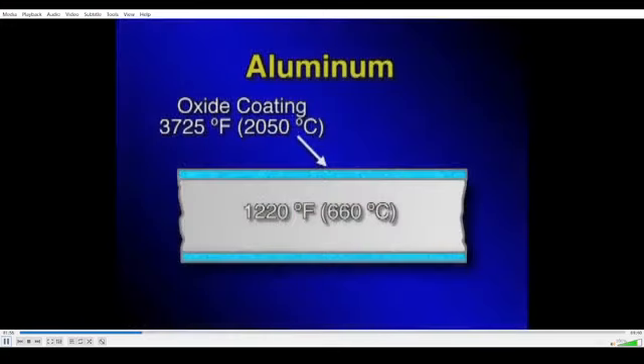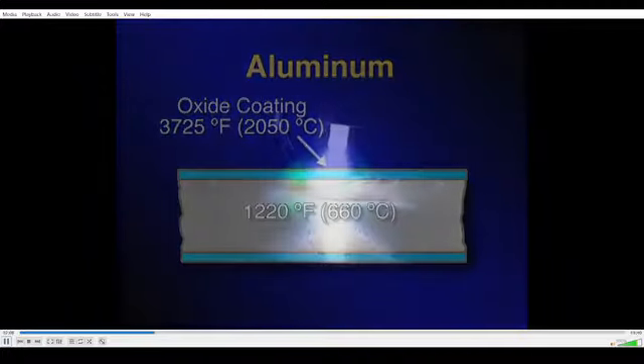For another, aluminum oxide melts at approximately 3,700 degrees Fahrenheit or 2,050 degrees Celsius, while aluminum melts around 1,220 degrees Fahrenheit or 660 degrees Celsius. If you try to weld with the polarity set to DCEN, the aluminum melts before the oxide. The puddle forms under the oxide coating, preventing the molten aluminum from fusing properly to form a sound weld. Compare this to the bright, shiny puddle produced with alternating current.